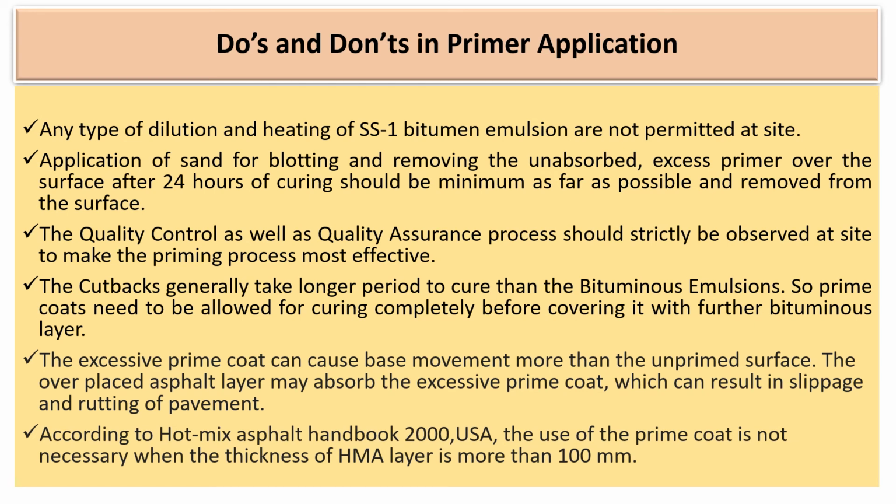A more interesting piece of information obtained from the Hot Mix Asphalt Handbook 2000 is that the prime coat is not at all necessary when the HMA, popularly known for hot mix asphalt layer, above the granular base course is more than 100 millimeter thickness.